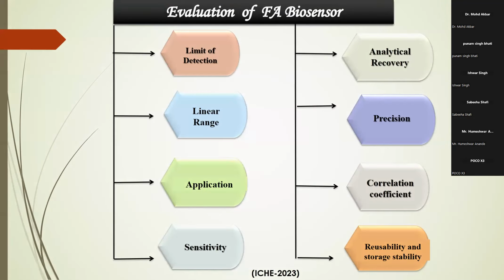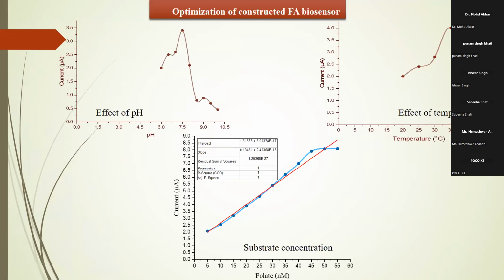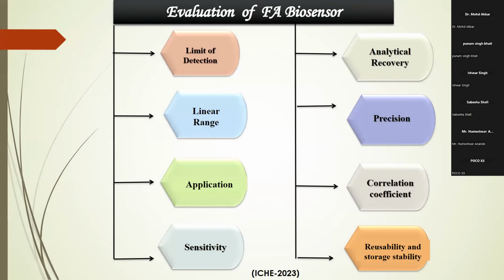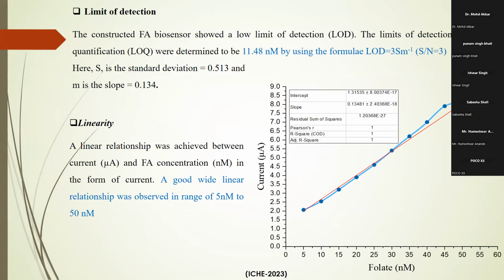Optimization was done by taking pH, temperature, and the substrate concentration was also checked. And here is the evaluation that was done of the constructed folic acid biosensor. Now the 11.48 nanomolar limit of detection was determined by using this formula, taking the signal to noise ratio equal to 3, and a good linear relationship was obtained between 5 nanomolar to 50 nanomolar.